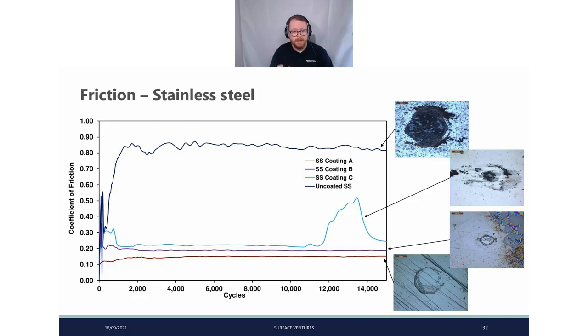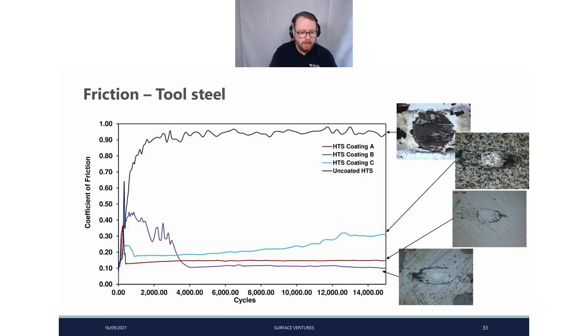So we can see here quite nicely as they separate by H/E ratio, like I talked about earlier. So our highest H/E ratio, coating A, lowest, then B, then C, and then uncoated right at the top, with extremely high coefficient of friction, as you would expect from an uncoated sample. And you can note the change in the morphology of these. Tool steel, once again, very similar. A little bit more dynamic changes with this throughout the cycles.